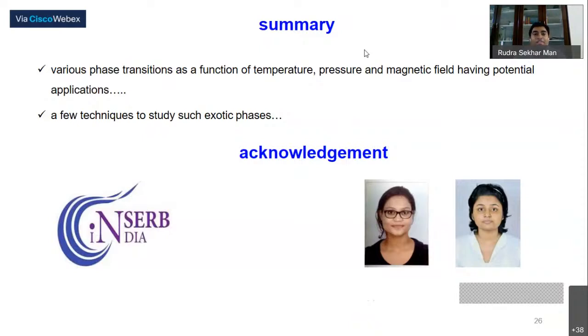But there are certain systems, like the ones I showed in my presentation. There, because of thermal fluctuation, although the spins have a nice correlation, the thermal fluctuation is so large, from the energy scales point of view, that you don't see the magnetic energy scales. The moment you reduce the temperature, you are suppressing one energy scale, and your magnetic energy scale tries to show its effect. So that's why you have to do it. In a system you have to know how much magnetic energy, how much magnetic field you need to observe such an effect. That is the definition, nothing else. The temperature variation is the way people see how the magnetic energy scales.